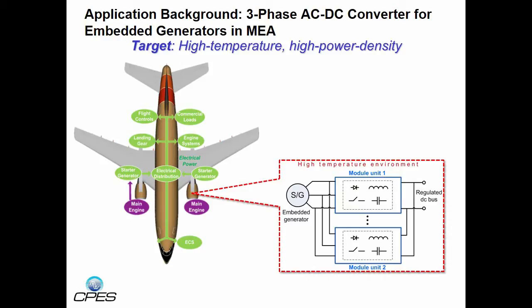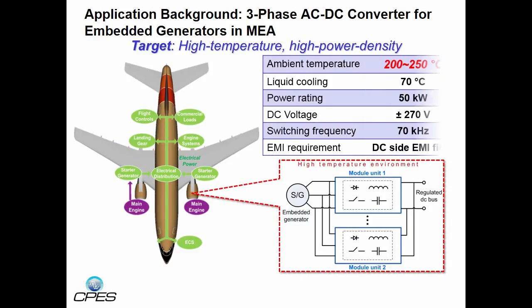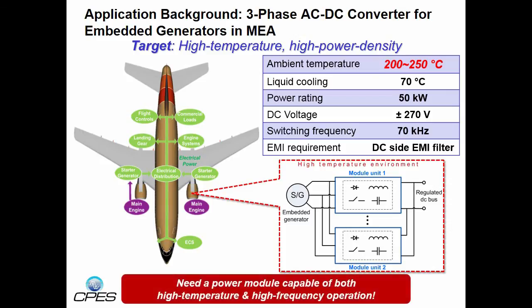Consequently, this work aims to demonstrate a fully high-temperature, high-power density 50 kilowatt converter with 70 degree C liquid cooling, plus minus 270 volt DC rating, and 70 kilohertz switching frequency. These converters can be interleaved to achieve the full 150 kilowatt power rating. At the time of this project, no high-temperature power modules were commercially available. Therefore, part of this project involved the design and fabrication of power modules rated for 200 degree C operation.